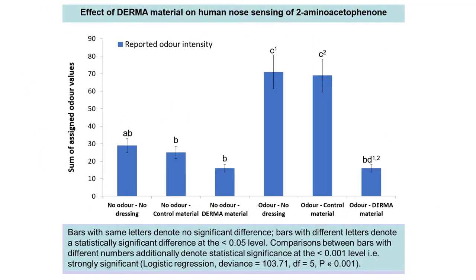The results indicated that the DERMA activated carbon material was able to significantly reduce the odour present in the laboratory testing procedure as assessed by healthy human volunteers. This is indicated by the significant reduction in the bar height indicated here in the very last column on the chart. It can also be seen that the score is as low as that of the sample with no odour, also covered by the DERMA activated carbon material. This indicates that the activated carbon material was able to eliminate any background odours, such as the plastic used to house the samples, when compared with the samples that had no covering or the control material.